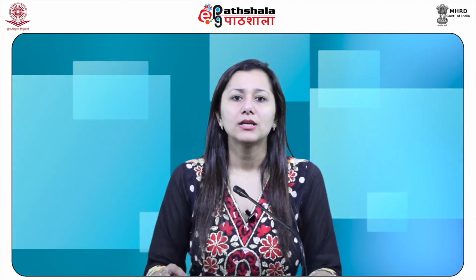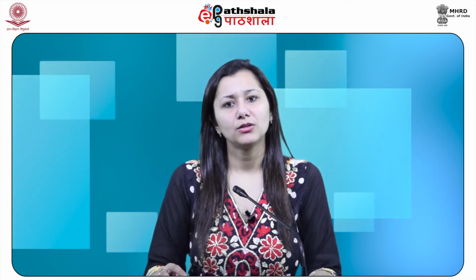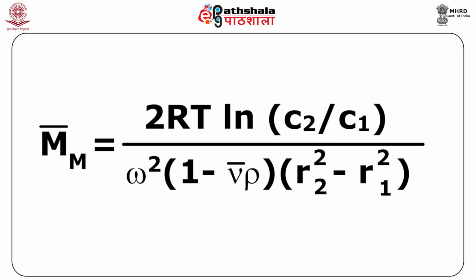By using the sedimentation equilibrium method, molar mass of polymer can be determined by M bar equals 2RT ln(C2/C1) divided by ω² (1 − V bar ρ)(R2² − R1²), where ω is the angular velocity of the rotor in radians per second, ρ is the density of the solution, C1 is the concentration at a distance R1 and C2 is the concentration at a distance R2 from the axis.